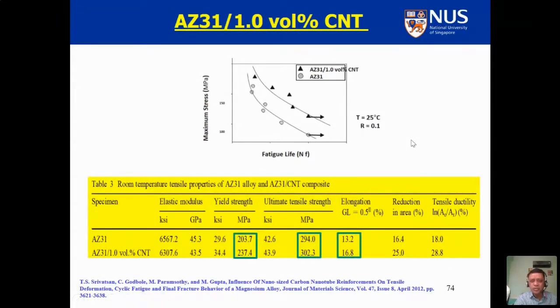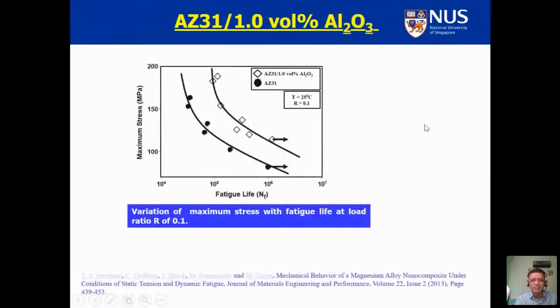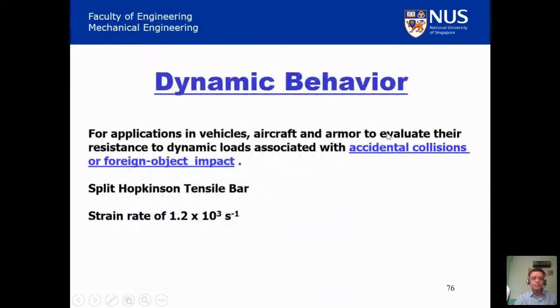So not only are you improving the property in the static condition, but you are also improving the property in the cyclic condition of loading. Similar results you can see from the reinforcement of Al2O3 at the nanoscale: for a given stress, the number of cycles to failure for a nanocomposite is higher.